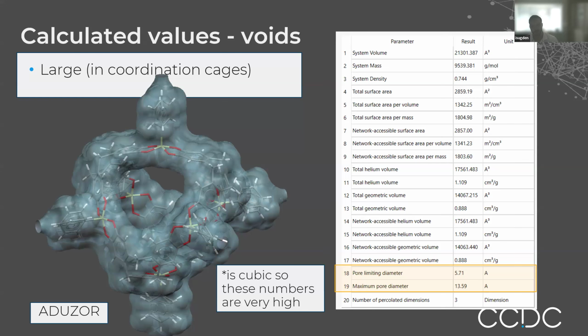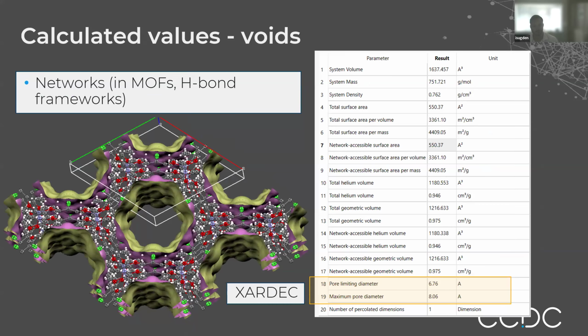And then finally, we've got an example of a very large void crystal, I should say. So this has a large diameter and actually quite a huge volume. And in fact, if you look at the system density, you can see that if this crystal structure didn't just absorb water, it would be lighter than water and would float on it. And so with this sort of system where you have very large pores propagating through the system, you can make predictions on what application it would be useful for and potentially able to take up a large amount of gas, for instance, in the carbon capture industry.